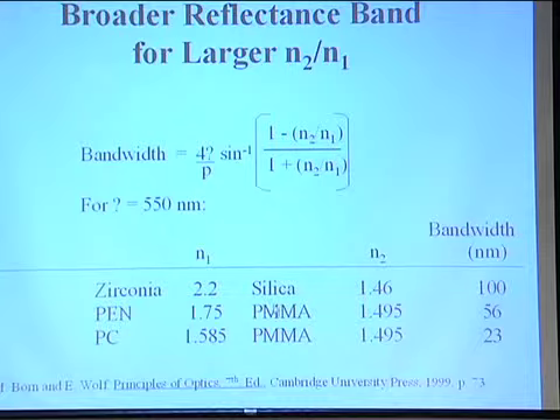Prior to 3M coming up with this technology, people were making these mirrors, interference mirrors, on glass by coating the glass with a real low refractive index silica and alternating it with layers of a real high refractive index zirconia. You can get good mirrors that way, but it's an expensive batch process. You got to go layer by layer. And then there was another company actually before 3M too that made some of these films with polycarbonate and PMMA, but